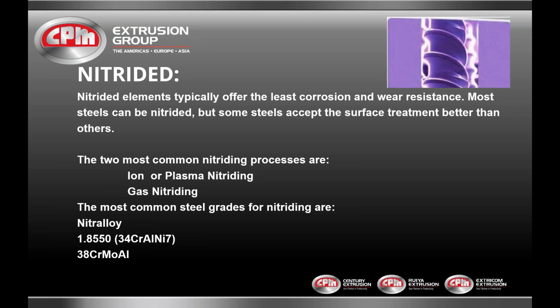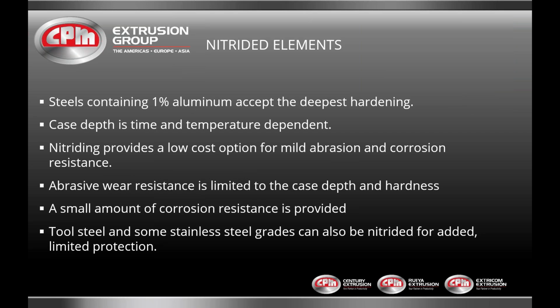The most common steel grades are nitraloy, typically nitraloy 135M, 1.8550, and 38 chrome moly and aluminum. The steels containing 1% aluminum accept the deepest hardening. Correct time and temperature for the particular alloy and desired results are critical to proper nitriding. Nitriding provides an economical option for mild abrasion and corrosion resistance, limited to the case depth. Tool steels and some stainless steels can be nitrided to add limited protection.